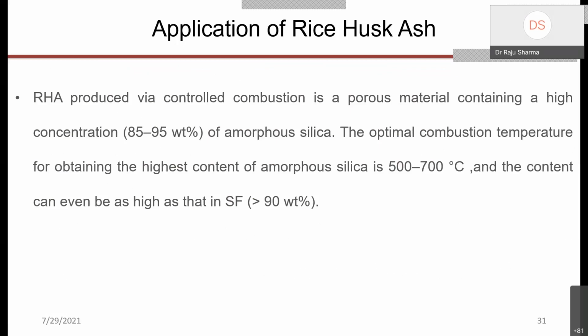RHA produced by controlled combustion is a porous material containing a high concentration of silica, more than 90%. The optimal combustion temperature for obtaining the highest amount of silica is in the range of 500 to 700. I told you this is the range; you cannot get a good result from a single temperature. So 500 to 700 degrees Celsius is the range, and the silica content can be even more than 90%.